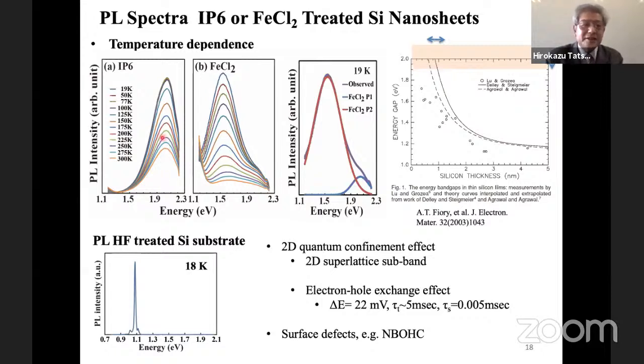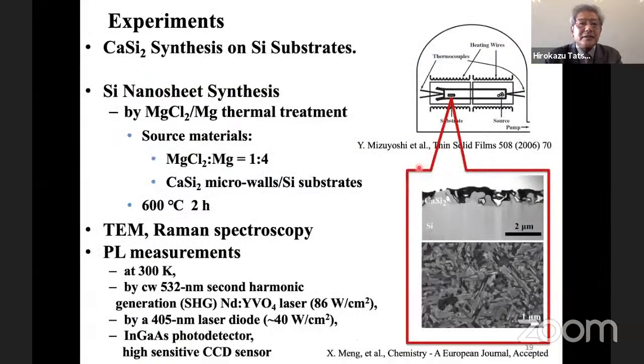So we discuss this luminescence. It's caused by the periodic structures of the silicon nanosheet, originally from the CaSi2 template. Then we extract calcium and make silicon nanosheet. Then we add magnesium atoms into the silicon sheet, using these materials.